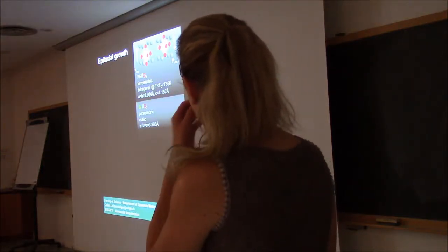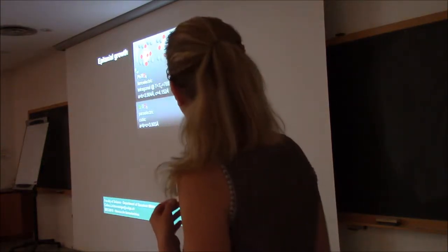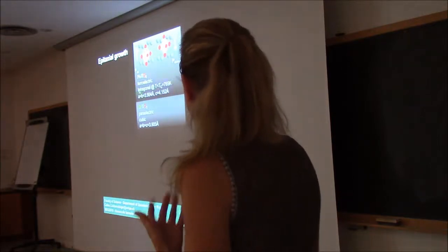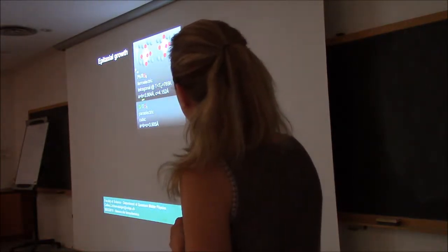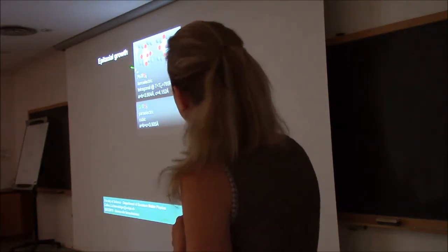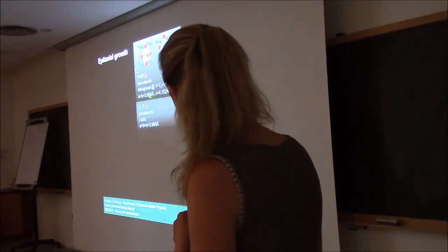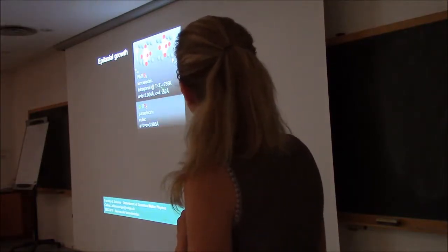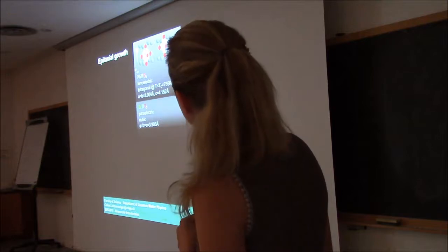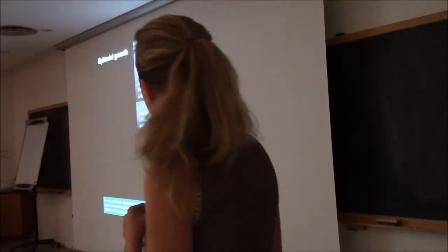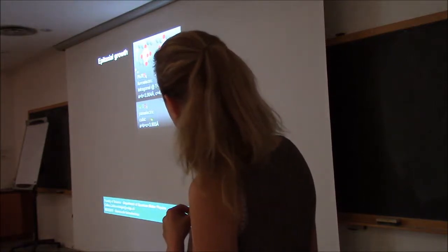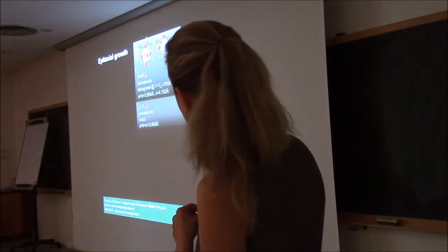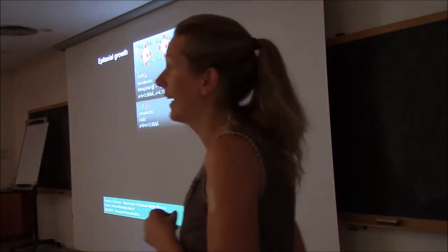Here I'm focusing on PTO, lead titanate, which is ferroelectric and tetragonal at room temperature, with an in-plane lattice parameter of 3.904 and a c-axis parameter of 4.15. If we work with strontium titanate, which is paraelectric and cubic, the lattice parameter is 3.905. So when you grow this material on top of strontium titanate, yes?